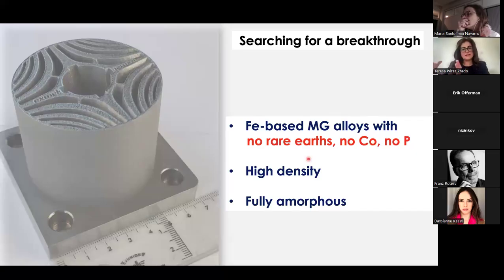When I say we are, it's an entire consortium that I'll introduce you in a minute. But we wanted to do this, to make a bulk, complex shape component, fully amorphous, fully dense, and also with an iron-based metallic glass with a very specific composition. So with no phosphorus, because this is very volatile, with no cobalt, because of the large societal impact of cobalt, and with no rare earths, because of the problems in supply chain and so on. And these alloys, like I was mentioning before, the glass formability is close to 100 microns.